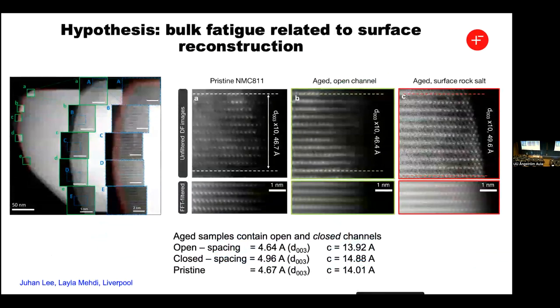Then, in collaboration with Layla Mehdi and her group in Liverpool, we were able to look at how the phases evolved as a function of cycling. In the pristine material, if you look at it with high resolution TEM, you can measure the spacings between the layers. As the materials age, you can see open channels, which is the edge of the particle where the layers go all the way out to the surface or the electrolyte. But you could also see blocked channels that had rock salt on them. What was interesting was that the spacings of the rock salt structure match the spacings at the top of charge before that collapse. So you get an absolutely perfect matching between the closed channels and the rock salt spacings.